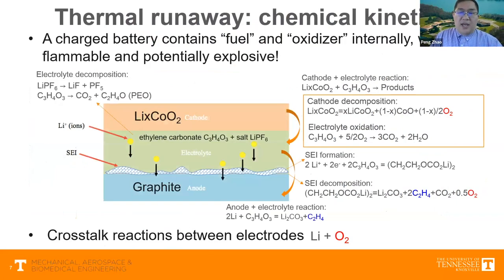So from the chemical kinetic perspective, I consider a charged battery contains a fuel and oxidizer internally. And what happens during thermal runaway, and here I gave you a very simple sandwich layer of lithium cobalt graphite batteries, where we can consider, say, the electrolyte fills a separator region that contains ethylene carbonate and some salt.